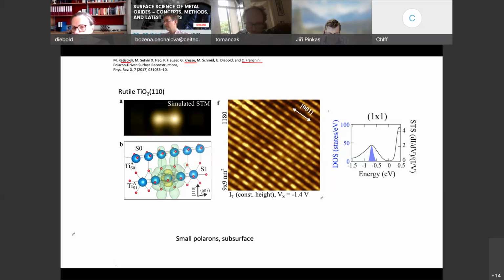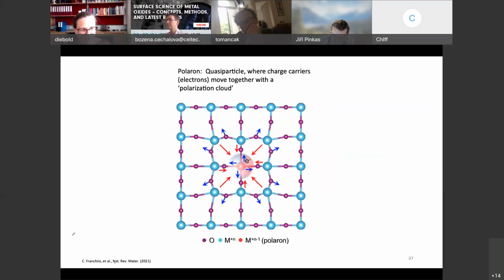Now, I could talk about these extra electrons in lots of detail. Actually, we've just published a paper this year in Nature Reviews Materials. We talk about these extra charge carriers because these are what people call polarons. These are quasi-particles where a charge carrier, an electron, hops from one site to the next, to the next. In an ionic lattice, you have a metal and an oxygen, and the metal is positive. You put an extra electron here, and the extra electron will push away the negatively charged oxygens and attract a little bit the positively charged titanium atoms. So there's a distortion in the system.